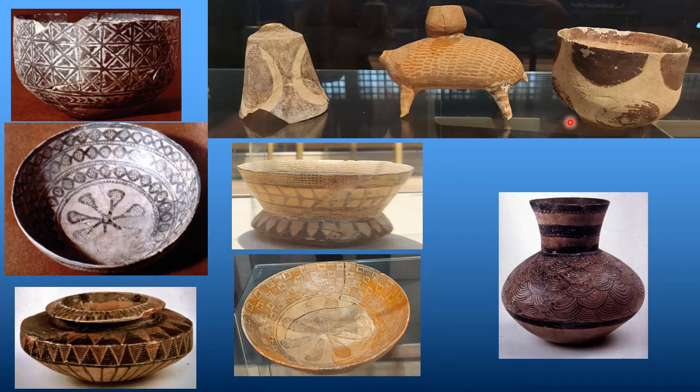So it's hand formed, if you will, and it's fired in a 2-chamber kiln, which is another important thing because it suggests that they understand the use of oxygen in the firing process to give colors. Like when you look at these things, we call them painted, but it's not really paint. It's actually like the finest levigated clay, and then you're playing with the amount of oxygen in the kiln to form these colors. It's just absolutely amazing, really, when you think about it. Some of the vessels are in the shape of humans, also animals.